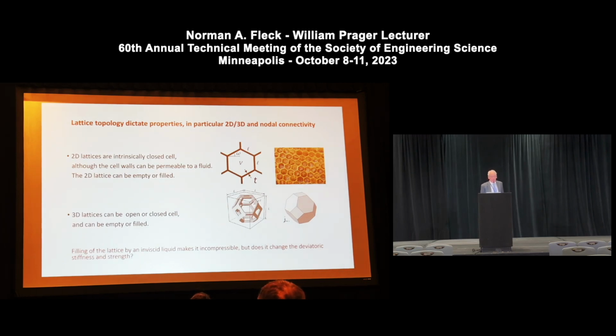Okay, so the first take-home message that I'd like to point out is that the topology matters, and in particular nodal connectivity matters. The hexagonal honeycomb, if you just look at the nodal connectivity, you see it's 3, and a result which Vikram and Mike Ashby and myself introduced is the sensitivity of the structure to that nodal connectivity. If the nodal connectivity is 4 in 2 dimensions or 6 in 3 dimensions, that's the transition point where you might expect the lattice to switch from deforming in a bending manner to a stretching manner.